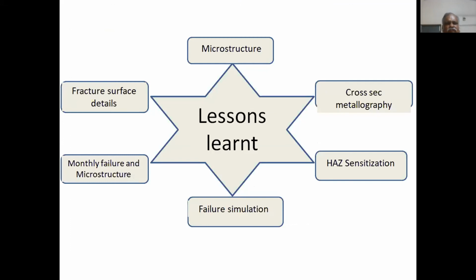So with this, I will try to conclude saying that microstructure is very important, and what you do not see with your eyes can be seen through the microstructure. With the help of microstructure, a fracture surface study will reveal certain details. The cross-sectional metallography will reveal certain microstructure evolution in terms of the precipitation, in terms of the dislocation structure, in terms of the bands, deformation bands, etc. I have provided 3 case studies. One is the monthly recurring failure of wire rope, and I showed how decarburization is the cause. I also showed HAZ sensitization of the material, which can cause a failure, and the failure simulation done by our mechanical engineers, why the crack has been a linear crack.